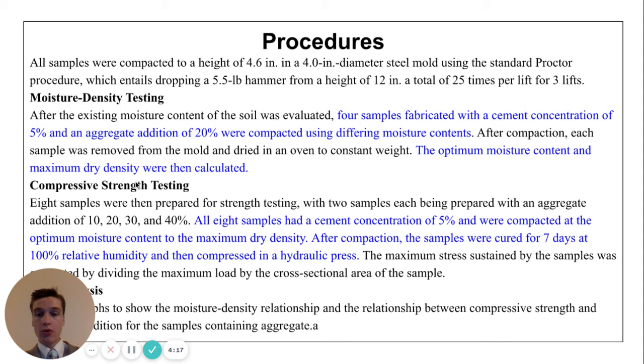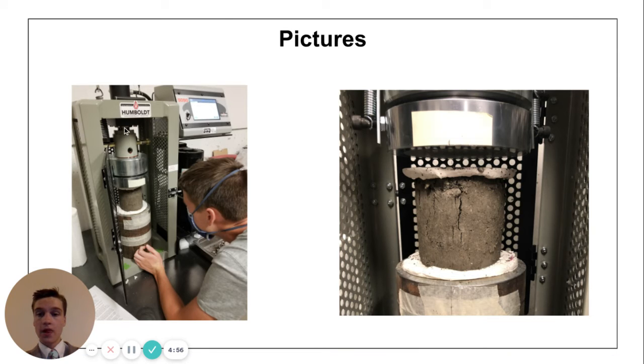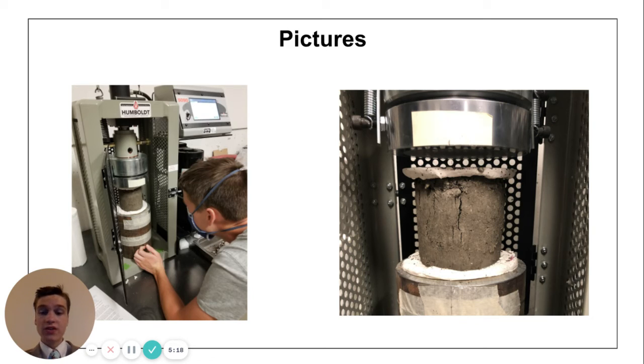For the compressive strength testing, I used eight samples. Each sample had a cement concentration of 5% and an addition of either 10, 20, 30, or 40% aggregate. After compaction, samples were cured for seven days in order to gain strength — this is an industry standard. After curing, I capped the samples. Capping involves putting the capping compound on each end of the sample to give a smooth surface for the hydraulic press, which is shown here, to exert a load and distribute it evenly across the whole sample. This sample has already been tested, as we can tell because of the cracks. This was a load failure test — this sample failed after over 500 psi, that's three tons, or 6,000 pounds.